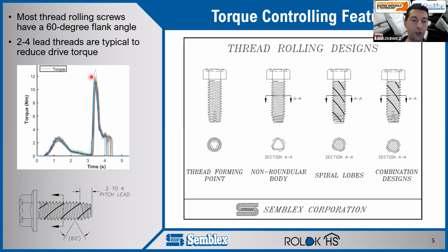Now we want a very large gap between these two peaks if possible, because we need to tighten to somewhere between these. If we tighten to less than the drive torque, then the fastener hasn't seated yet. If we tighten too high, then we risk breaking the joint. The bigger the range here, the better, and there's some different ways that we can control that, and that's where these torque controlling features come in.